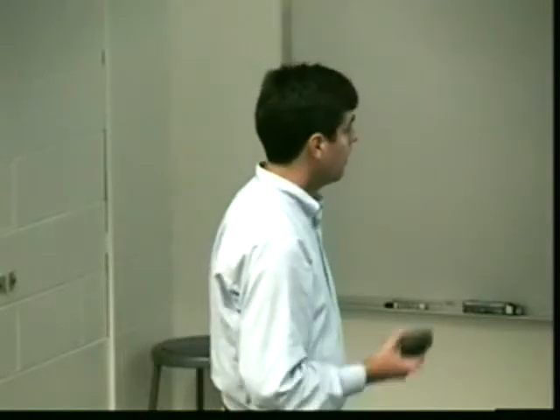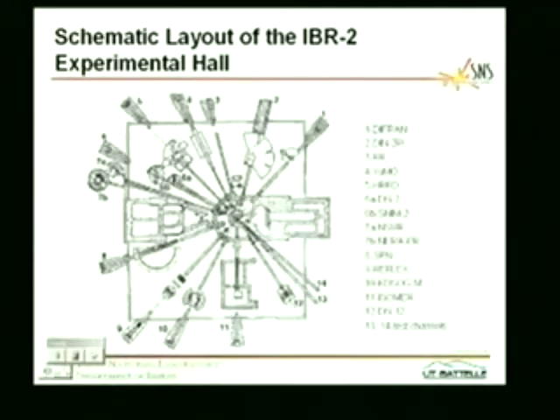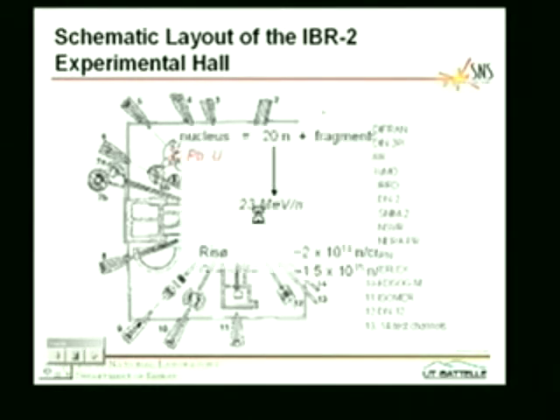So it's got an average power of 2 megawatts and a peak power in the pulse reflective of a 1,500 megawatt reactor. It never goes completely off, which is one of the issues. It sort of cycles, and it goes down to about 120 kilowatts in the off position. And it's got fairly broad pulses because it's just determined by this rather slow mechanical device, of about 320 microseconds, which is in some cases okay. In other cases, it's a little longer than you would want for time resolving your neutron velocities. And this just shows the experimental suite. So it also has a range of instruments that view moderators in close to the core.